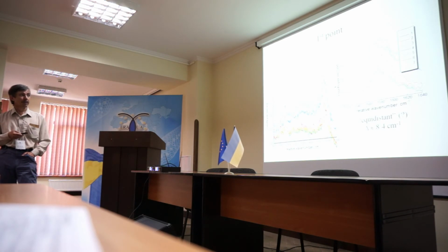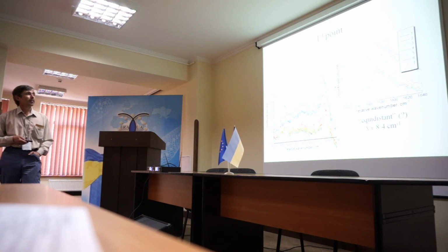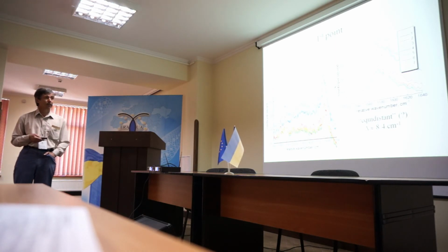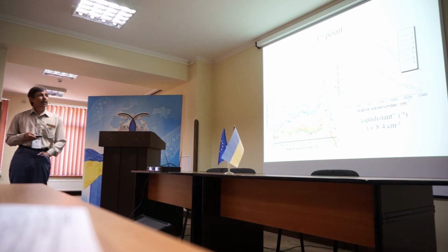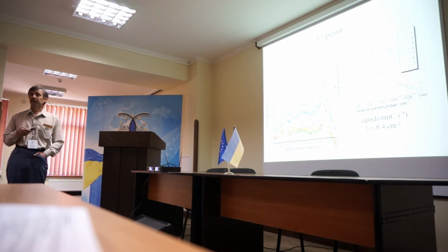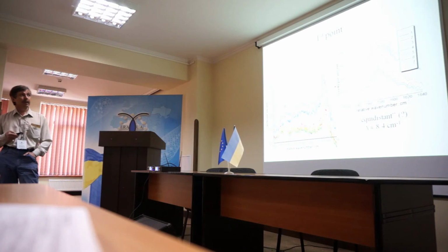Maybe the time between the measurements of this spectra was a couple of minutes, and at one point we didn't retract the tip, so we measured it with a repetition of a few minutes with a contact. And in the second case, we approached the tip, retracted it, then approached again, measured the next spectrum, retracted, and so on. You may see very good reproduction of the spectra.